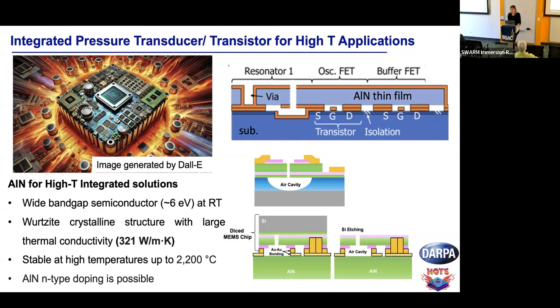A very thin layer. Thermal compression bonding? Yes. Why not gold? We did use gold also. Again, we haven't done the 800 C temperatures yet because we're still waiting for the measurement setup. It's not an easy one. We were a little worried that gold wouldn't be as stable at higher temperatures as platinum. With just our pads, we observed that platinum is a better material for 800 degrees C. But we have gold as well. We'll see which one survives better.